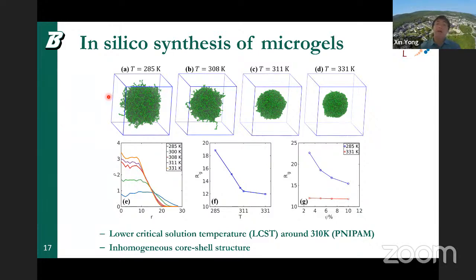And then we can parameterize our system, our DPD, to capture the temperature dependence. And this has also utilized our previous knowledge working on this type of hydrogel system. So as you can see here, we can capture these phase transitions where the microgel shrinks as temperature increases, and then the transition temperature corresponds well with the experimental observation. So this system is particularly representing a poly(N-isopropylacrylamide).